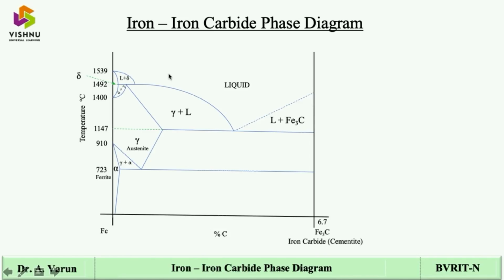Next important thing to do is about the compositions, that is carbon composition. We'll start at the top here, where the delta maximum composition is 0.1% of carbon. Then here in between, which is 0.18% of carbon, and the maximum here is 0.5% of carbon. And another one at this particular location, which is 4.3% of carbon, and then here it is 2% of carbon, and here it is 0.8% of carbon, and the maximum for alpha is 0.025% of carbon. At room temperature, alpha is 0.008% of carbon.